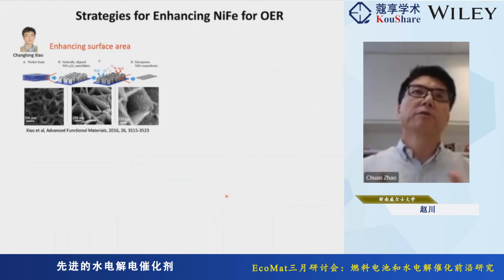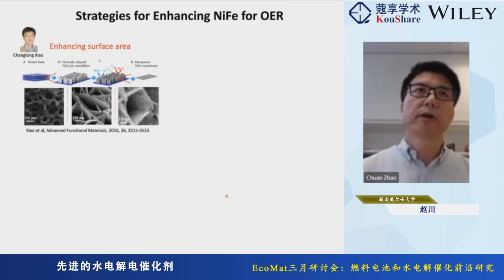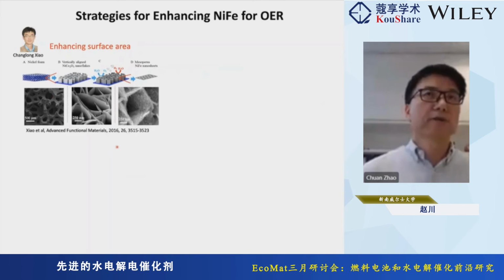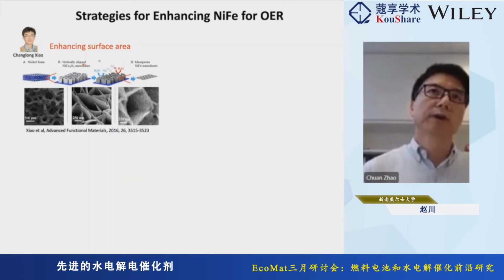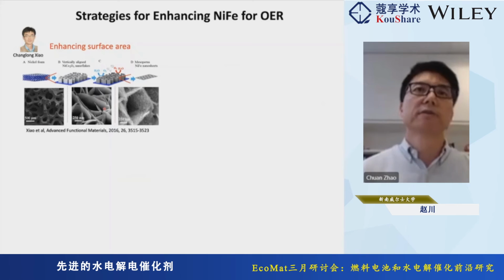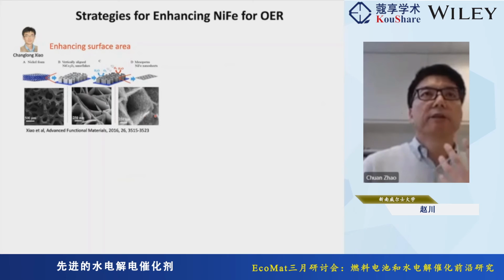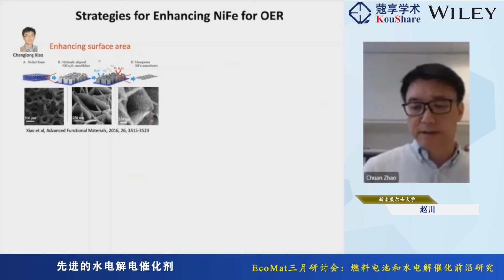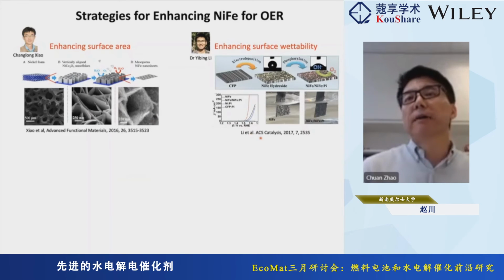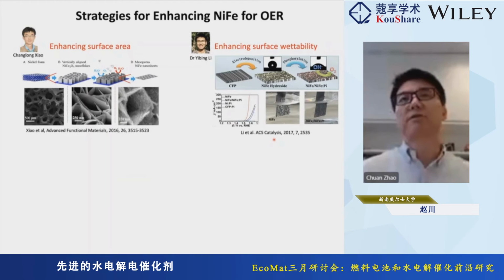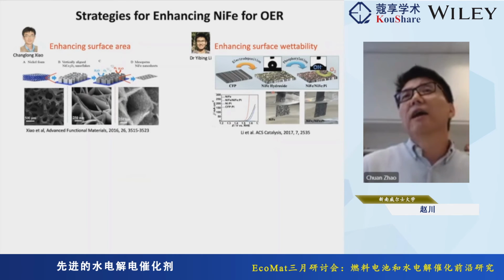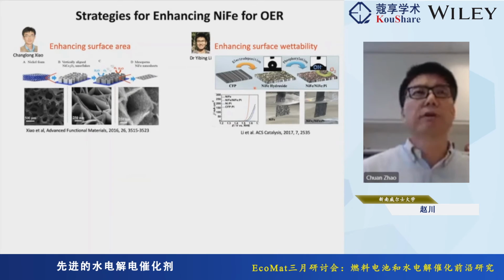After that, we looked for strategies to further improve the activity of nickel iron. For example, Xiao, who was a master's student in my group at the time, introduced a simple engineering approach to enhance the surface area. Before depositing the nickel iron directly onto nickel foam, he added another layer of vertically aligned nickel oxide nanoflakes, and on top of that surface we then deposited our nickel iron nanosheets. We got an enormously enhanced surface area as well as activity. And Yibing, who was a postdoc in my group and now I think is a professor at Southwest Jiaotong University in China, was looking to change the surface property of the nickel iron.